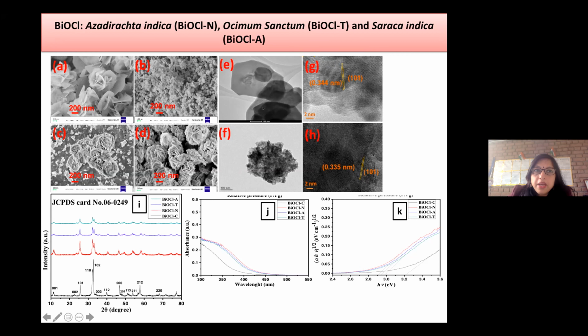You can see E is the image of BiOCl prepared by the hydrolysis method, and F is the green one, meaning tulsi, neem, ashoka. So you can see the size. Here you can see the big plates from hydrolysis, but when we modified the method, the plates were converted to smaller ones. So if more surface area is available and if we can reduce the electron hole recombination, then obviously the photocatalytic activity will be better.